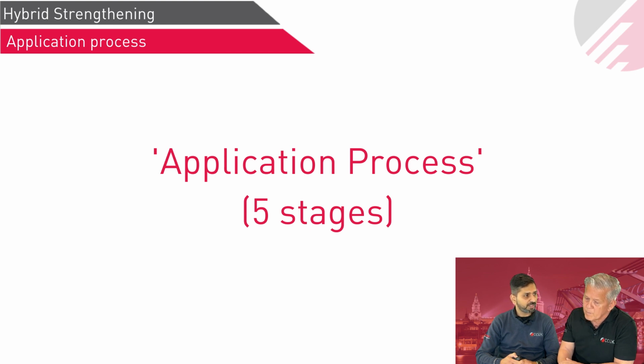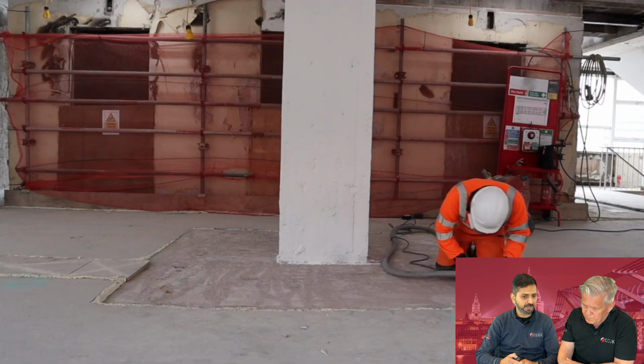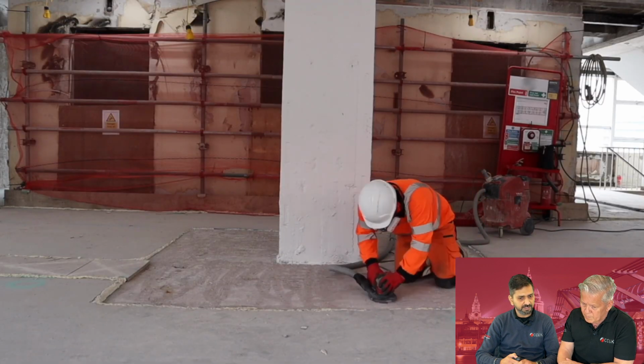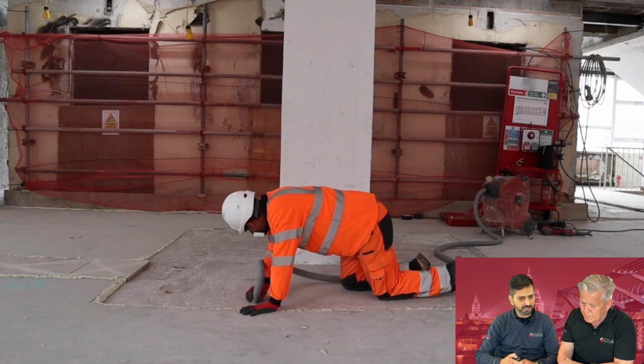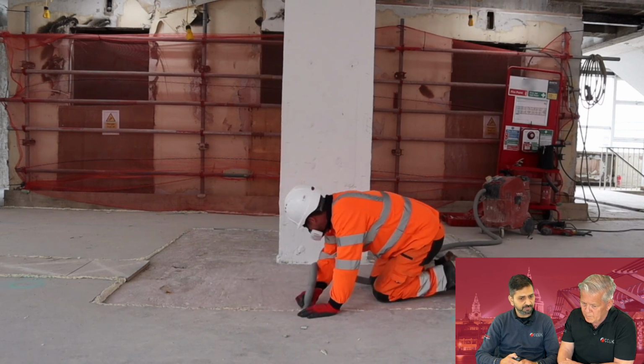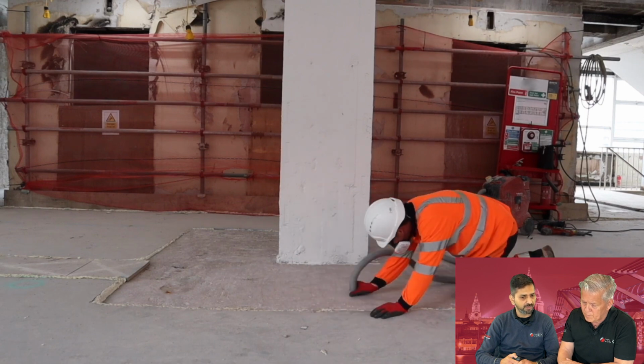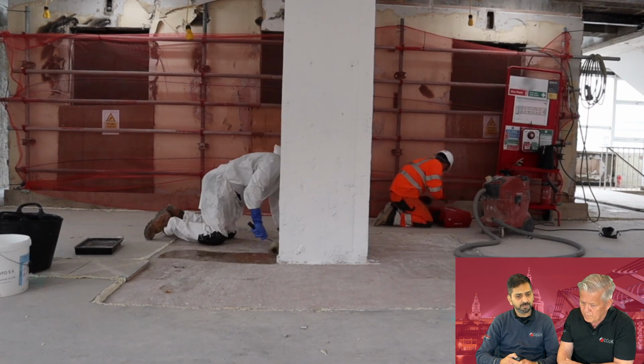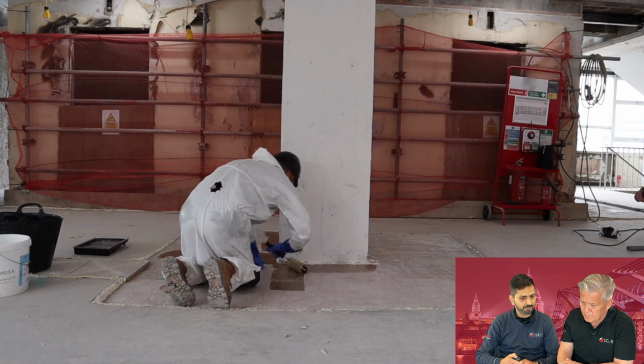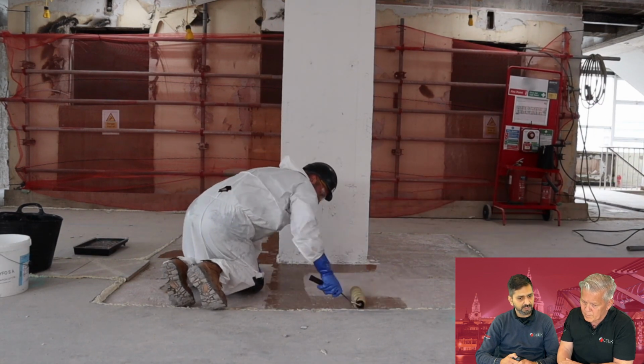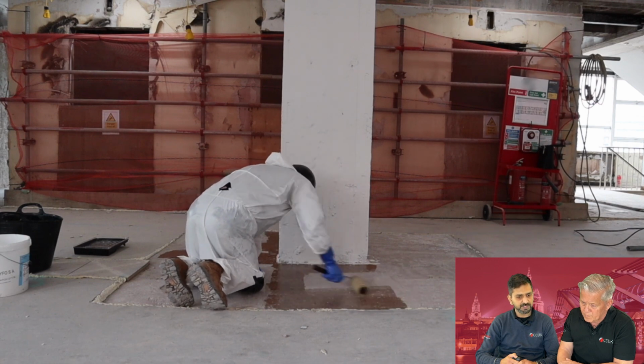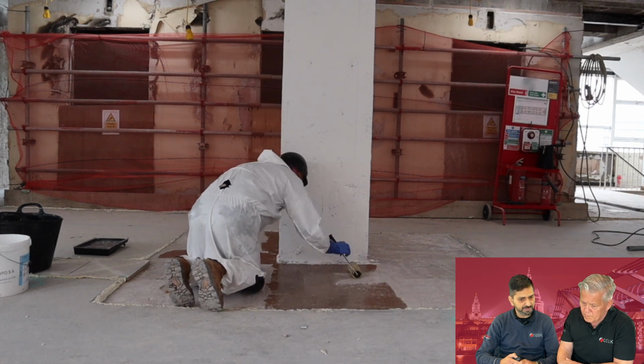For that reason, we do not subcontract the application. It is done by our own guys who are employed by us, purely to have that control over the application as well. The process is, first you prepare the surface, which is normally done by diamond grinding, followed by cleaning of the area, because you need a dust-free surface to apply carbon fiber. Then they prime the concrete using pure epoxy, so it can soak into the concrete. Then they apply the first coat of thickened epoxy, which is the white epoxy we are seeing, and they unroll the first layer of carbon fiber. Then another coat of epoxy, then another layer, and that's how they build up the number of layers according to the design.